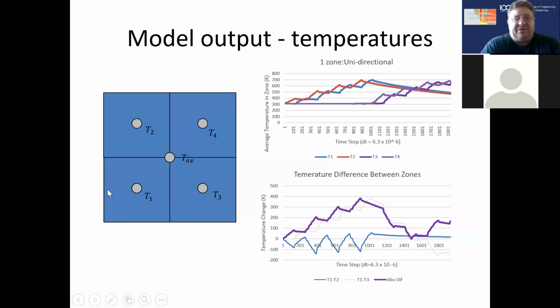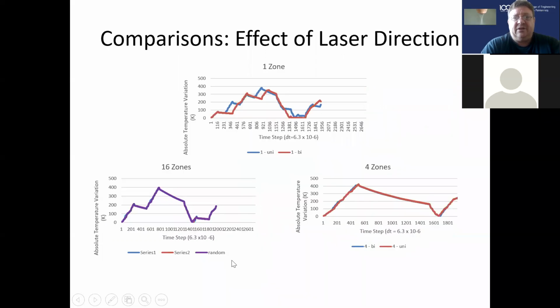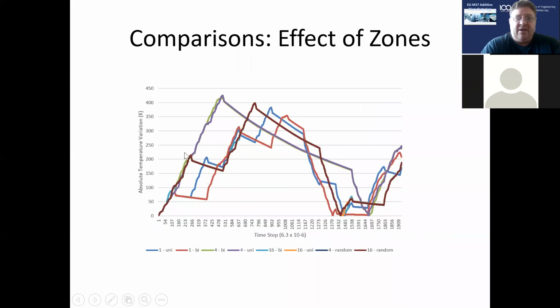The sort of thing that we can do is average the temperatures in these different zones, and we can look at trying to even out the temperatures, the peak and lower, higher temperatures in all the different zones. When we start putting all these temperatures together from all the different types of hatch patterns, we can see why some of these give us high peaks and troughs, and others, like the 16 sort of checkerboarding pattern over the same zone, give us slightly lower peaks and troughs, but maybe a slightly higher average. But the net effect of some of this could be to reduce the residual stress.